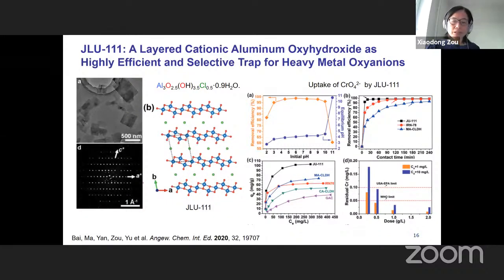And we have also studied other types of materials. This is a layered cationic aluminum oxyhydroxide. Most of the zeolites are anionic, so they are negatively charged. And this one is positively charged, which means it can absorb negatively charged anions, for example, heavy metal anions. And this structure was also determined by electron diffraction. You see it's a layered structure, and here chloride is between these layers, but this chloride can be exchanged with other anions, for example chromate.